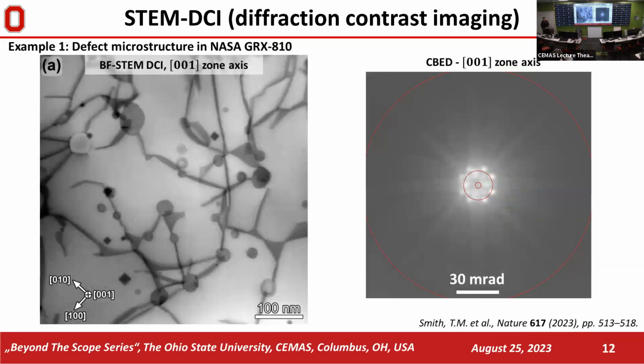So this brings me to example 1, where we used diffraction contrast imaging of the structure in the GRX alloy, where we exclusively started with zone axis imaging to get all possible G's creating the contrast in our image. And this is an ultra-polished disc foil, several hundred nanometers thick, and the image was obtained with a probe-corrected TEM.